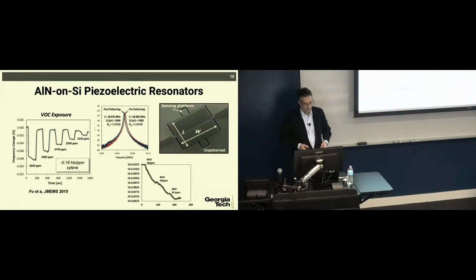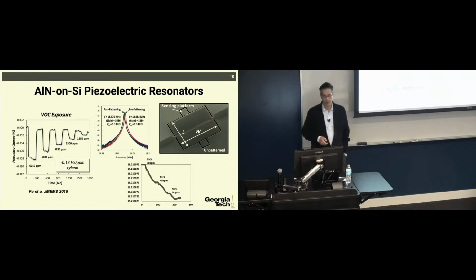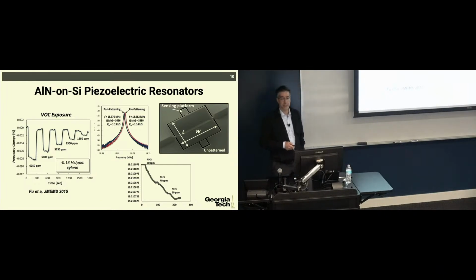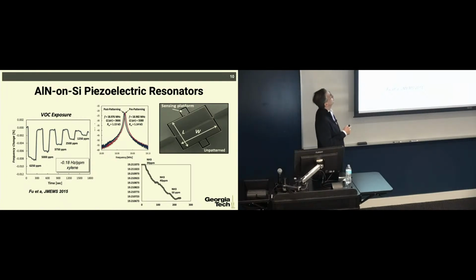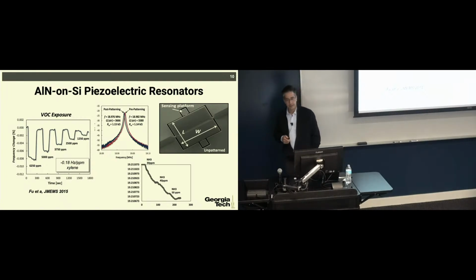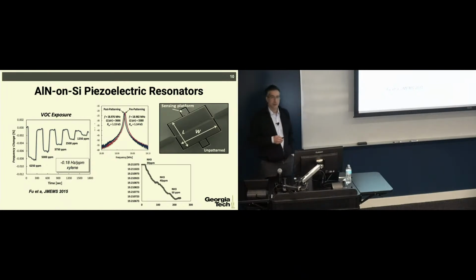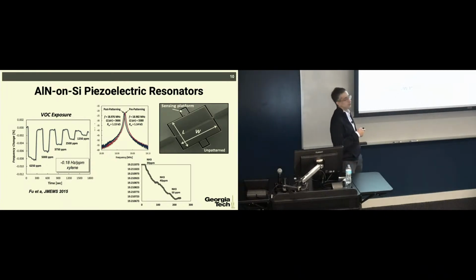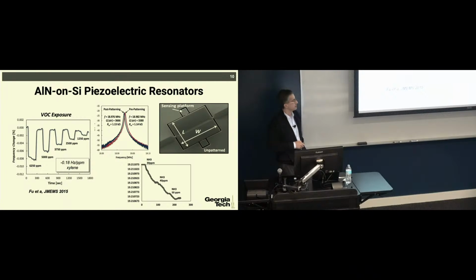All right. Now let's switch from capacitive to piezoelectric. It was around 2007 and 8 that very high quality thin film piezoelectric materials became available. And that was basically aluminum nitride. Aluminum nitride, it's a benign piezoelectric material, meaning that none of these are going to hurt the CMOS process in terms of being a nasty doping for CMOS. So it could be integrated with CMOS or processed at the CMOS foundry.